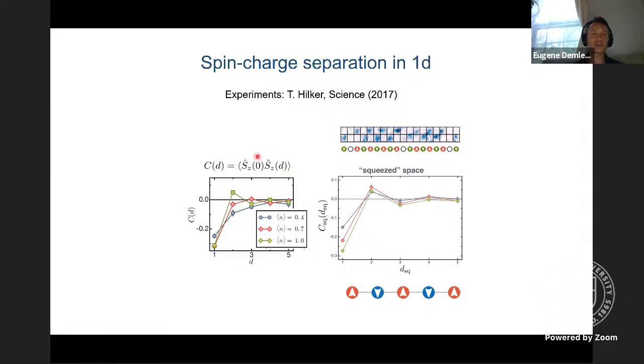If you see, when they look at just the usual two-point correlation functions at half filling, you see that nearest neighbors have antiferromagnetic correlations, and they become ferromagnetic, then they become again antiferromagnetic when sites are further away, and so on. But as soon as we start doping, these oscillations of spin correlations are washed out very rapidly. However, when they take their snapshots, they can actually see where there is a hole, right? So here, you can actually see the positions of spin downs and spin ups, they're imaged separately. So they can remove the sites where there were holes and look at spin correlation in squeezed space. And now in squeezed space, correlations are the same regardless of the doping.